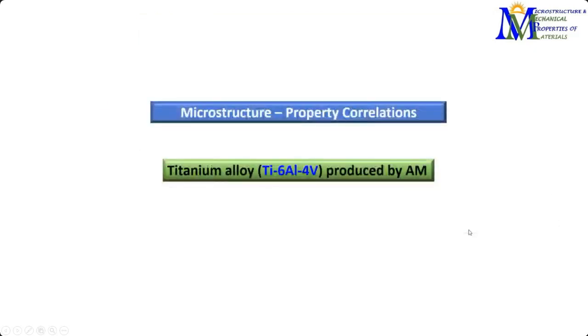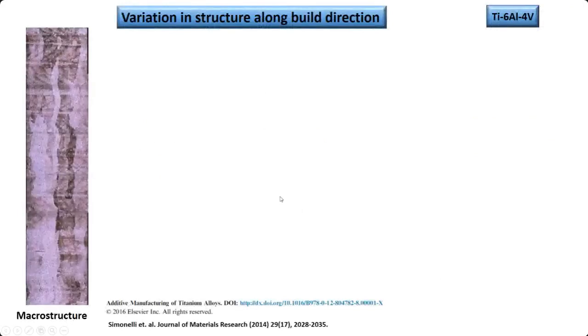Moving on to the most commonly used titanium alloy, titanium 6 aluminum 4 vanadium, which is a two-phase titanium alloy. It has two important phases, alpha and beta. The alpha phase is a comparatively low temperature phase, which at high temperature converts to beta, having a completely different crystal structure. Alpha has HCP and beta has BCC.